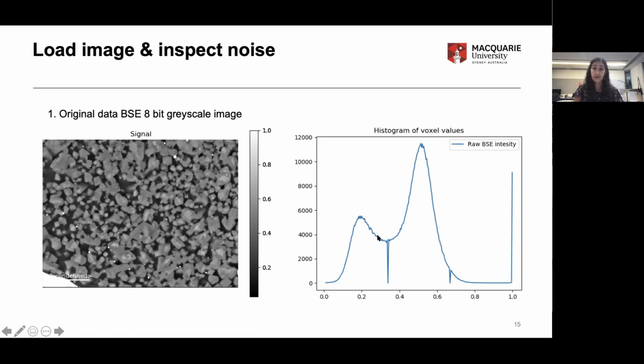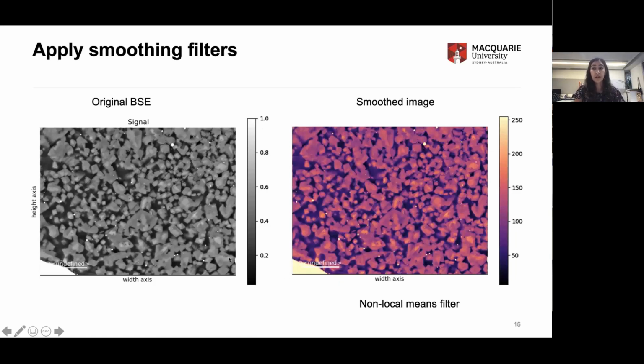So following uploading your image, we can apply smoothing filters. Our code has built in 2 filters, and we assume that the inherent noise within our grayscale image is of a Gaussian distribution. From there, we can apply 2 filters, a total variation filter and a non-local means filter. And that results in a smoothed image. These 2 images don't look particularly different, but if you pay attention to the edges of grains, the filters are actually enhancing that grayscale contrast between the bright grains and that dark background. And that's really what's key, because we need to be able to accurately pick out all of these grains. So by enhancing that contrast between background and foreground, that gives us a better chance of being able to identify grains and actually capturing that whole grain.